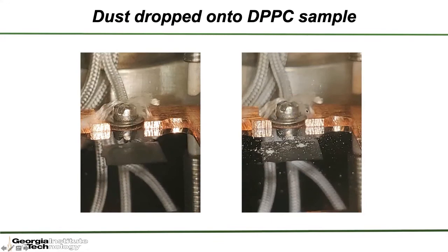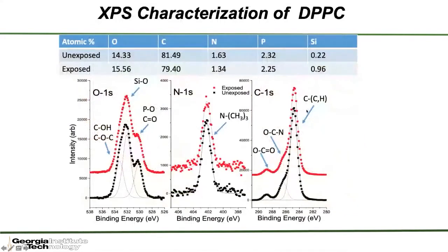And the technique that I'm going to talk about real quickly that I use to analyze the effects caused by these dust grains is called XPS, or X-ray photoelectron spectroscopy. And what this technique allows us to do is use X-rays to eject electrons from core levels of the various elements in our sample, and in particular from the uppermost several monolayers of our sample. And so only those regions that are almost certainly coming into contact with dust grains.